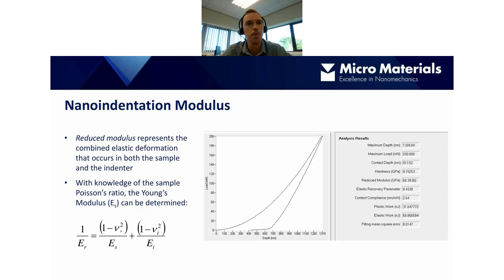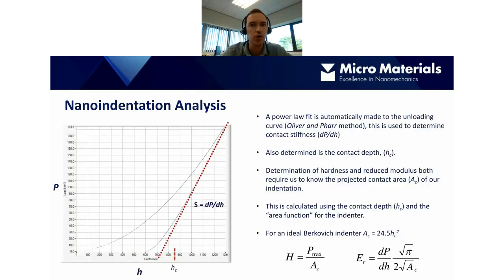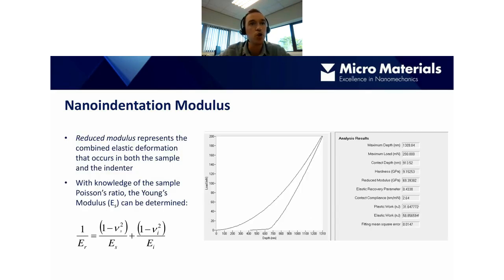So the equation we've just seen gives us the reduced modulus directly from the analysis of this indentation curve. The reduced modulus represents the combined elastic deformation from the tip and the sample. We can fairly easily convert that to the Young's modulus, or the elastic modulus, with this equation here. So we've determined the reduced modulus from the indentation. What we're after here is Es, which is the elastic modulus of the sample. All we need to know is this term here, which relates to the indenter material.